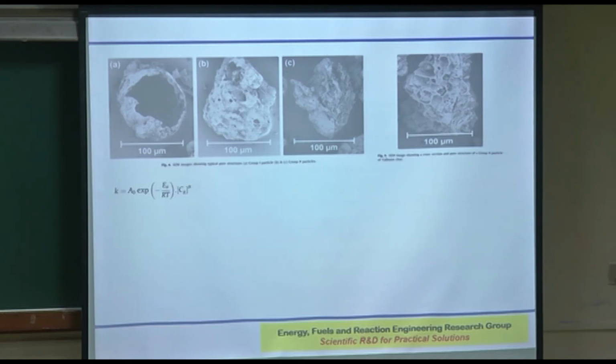So she's telling us that there is not much of a structural variation, partly hollow or fully hollow, and so hollow that the gases can go in and do whatever they want to do. It will take some time, but it can get the reaction going up to a certain conversion, until the ash content becomes dominating, with little carbon left and more ash, which will be difficult to convert.